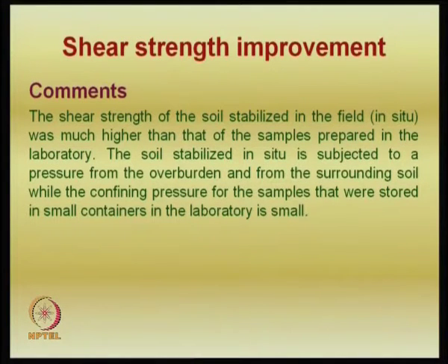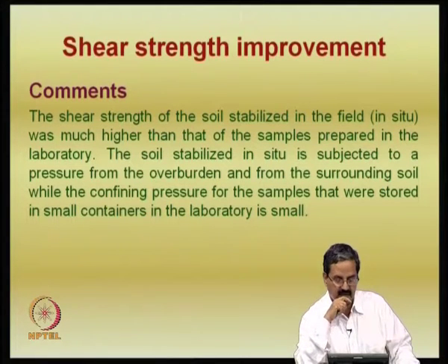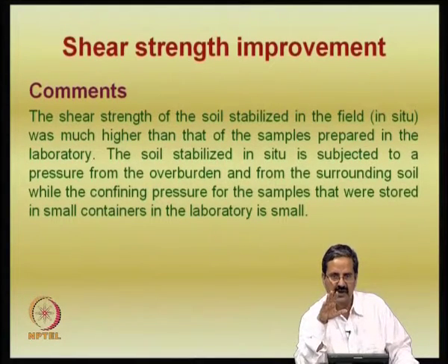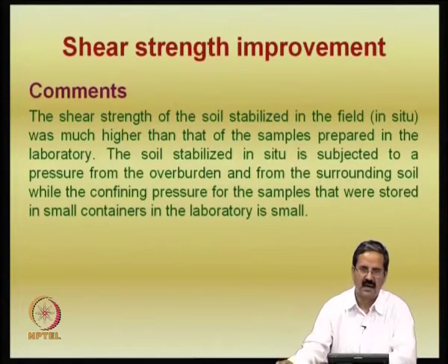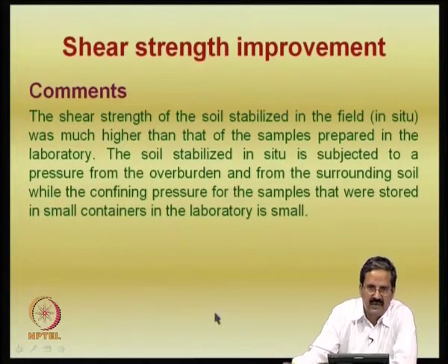And how is the strength of the soil improved? People have seen that, like you have seen just now, that the CBR is nothing but the strength of this in situ soil, and when you add lime, the strength of the soil is increased by about 30 times, 40 times, 15 times in some cases. In situ CBR tests were done in some cases, and we have seen that. You also saw the results of the unconfined compression tests from Professor Pala, where it was very clear. Even in our lab we have a lot of experimental results where it was very clear that the treatment using lime produces strength improvement.